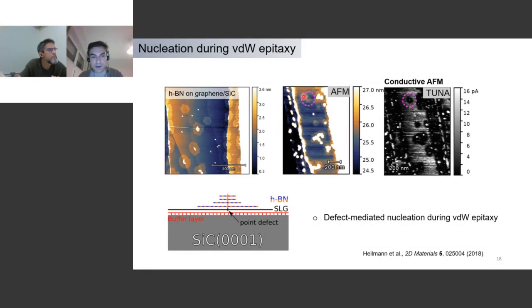But even if you go to specific areas where apparently you have a pure island growing on top of a graphene terrace, when we do some conductive AFM, meaning we are probing tunneling at the surface by using a metallic AFM tip, essentially the dark areas here correspond to a material that is insulator, and this is boron nitride in this case, while on the exposed graphene surface we have a higher conduction. That's what we're seeing here, and you can see that where we have these HBN islands forming, we have lower conduction, while in the other areas the exposed graphene is brighter.